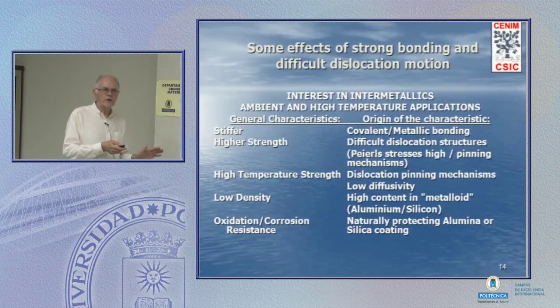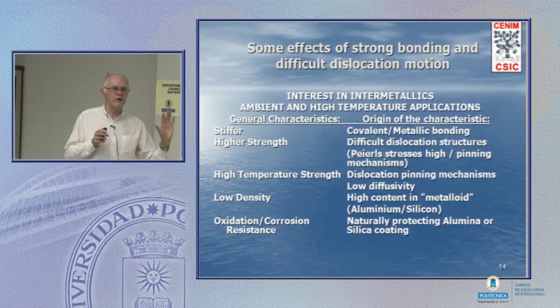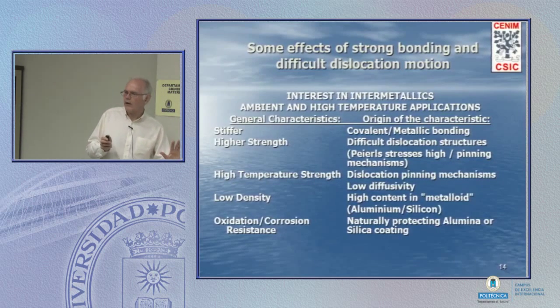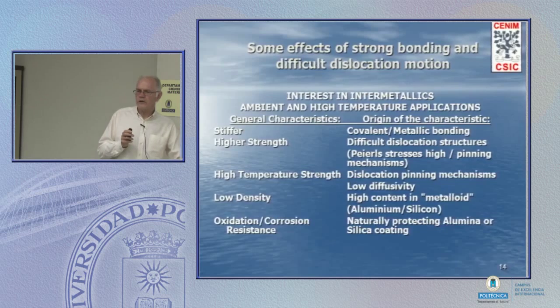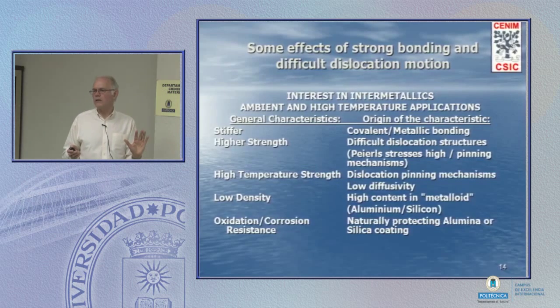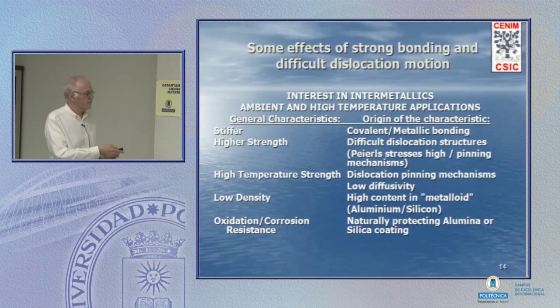Low density, what I've not said so far is that what we're always doing, in the structural applications at least, is mixing a transition metal with a light metal, especially aluminium or silicon. So if I mix a lot of nickel or iron with aluminium or silicon, I've got a much lower density alloy. And again, I've not talked about it so far, since we have a lot of aluminium or silicon, we're going to form a naturally protecting alumina or silica scale.